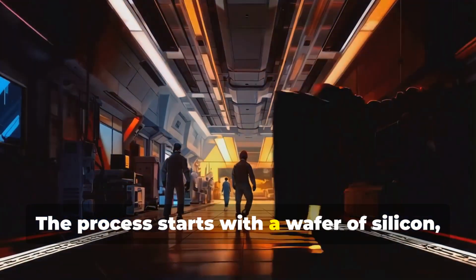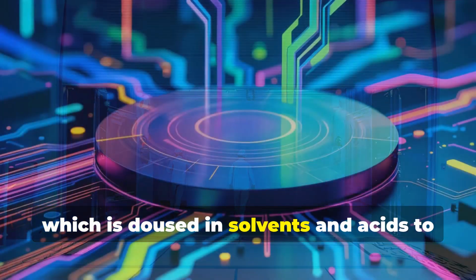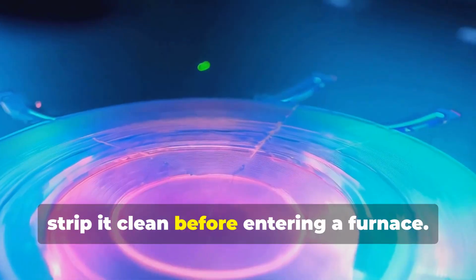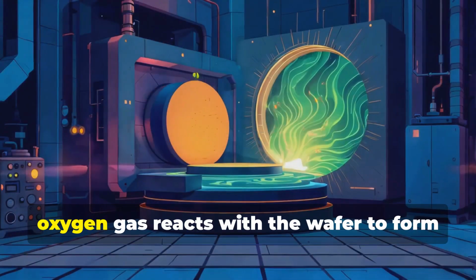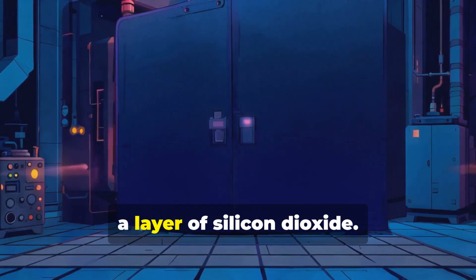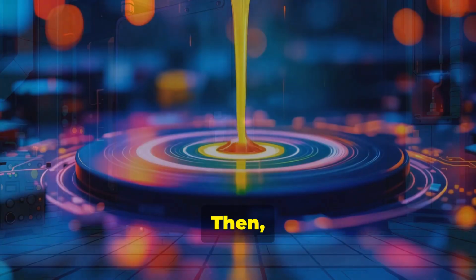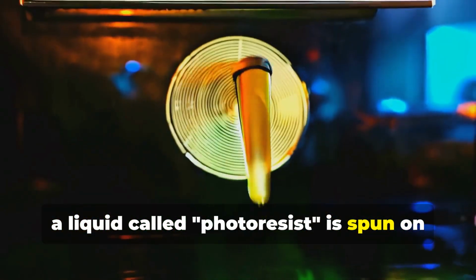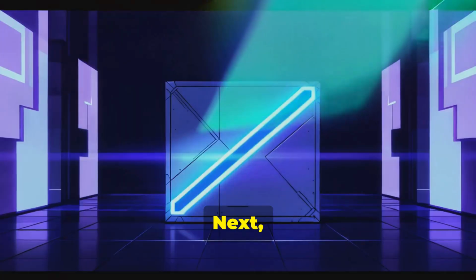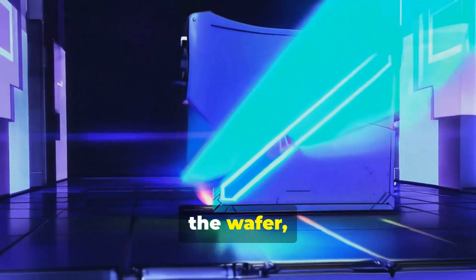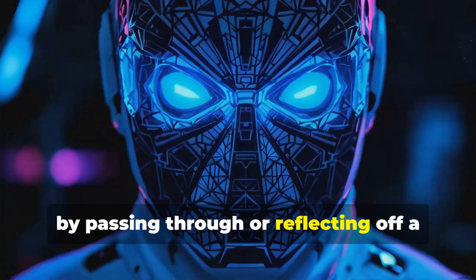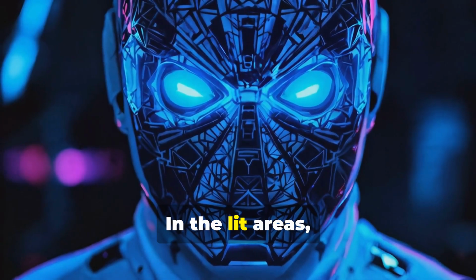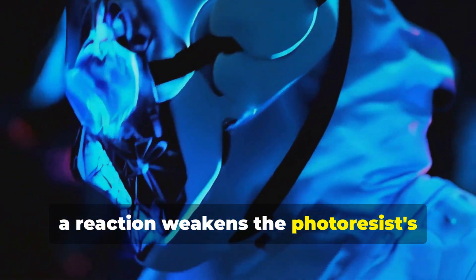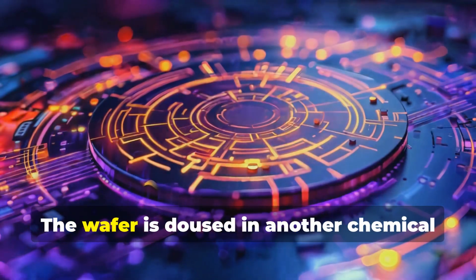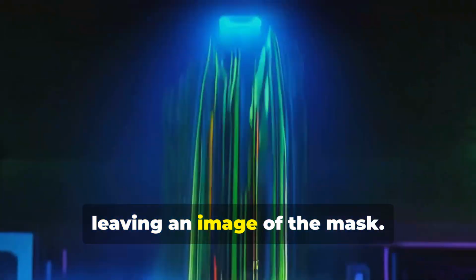The process starts with a wafer of silicon, which is doused in solvents and acids to strip it clean before entering a furnace. Here, oxygen gas reacts with the wafer to form a layer of silicon dioxide. Then, a liquid called photoresist is spun on and baked to harden. Next, ultraviolet light selectively illuminates the wafer by passing through or reflecting off a specialized mask. In the lit areas, a reaction weakens the photoresist's chemical bonds. The wafer is doused in another chemical to wash away that weakened photoresist, leaving an image of the mask.